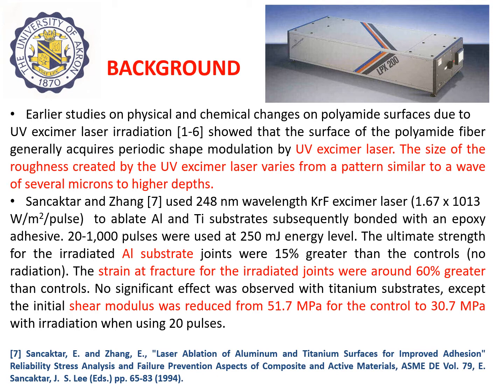We used 20 to 1000 pulses with 250 millijoule fluences. The ultimate strength of the irradiated aluminum substrate joints were 15% greater than the controls, and the strain at fracture for the irradiated joints were around 60% greater than controls. With titanium, we did not observe a significant effect for failure stress or strains, perhaps due to the strength and hardness of titanium substrates for the ablation conditions we applied. However, when we bonded the samples, the shear modulus changed from 51.7 for the control to 30.7 megapascal with irradiation using 20 pulses, showing a softening of the interface of the bonded joint.